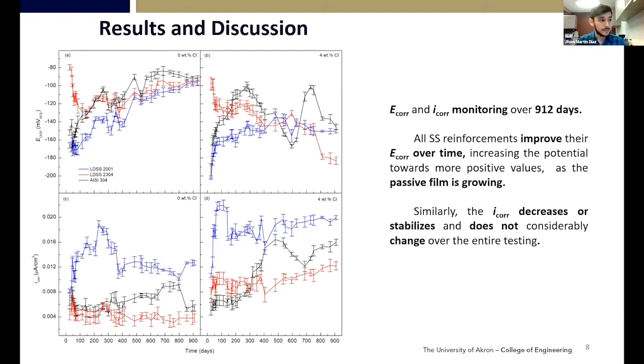This was also reflected in a higher current density. However, all 3 stainless steels were far below the limit for low corrosion by the standard, which was 0.1 microamps per centimeter squared, showing the good protection over this long exposure time of all 3 stainless steels.